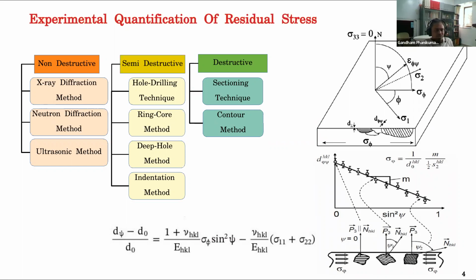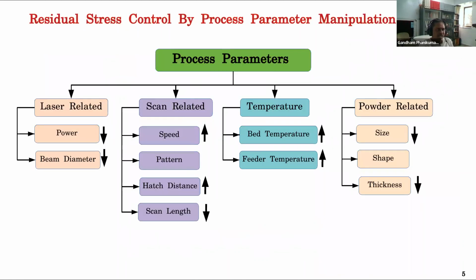So why we do it is because we want to bring the residual stress to a very small value so that there is no accumulation of residual stress as the component is being built, so that the component doesn't crack in the end. Okay. So we look at all the parameters and see which parameters affect the residual stress which way, because theoretically it can be done. And that will give us a hint on how to play with the processing conditions during printing so that the residual stress is under control.